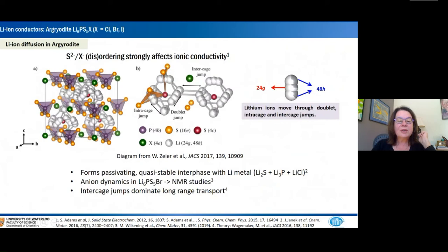These Frank-Kasper polyhedra cages contain these lithium clusters, and within these lithium clusters, there are different types of transport mechanisms for lithium ions. There is what is called a doublet jump between the so-called 48H positions and the 24G, which lies in the intermediate space between the doublet. And there's also the intra-cage jump and the inter-cage jump. The inter-cage jump is thought to dominate the long-range transport.